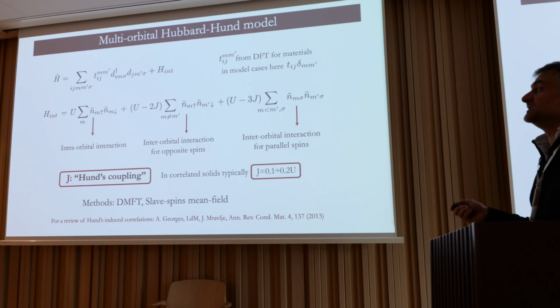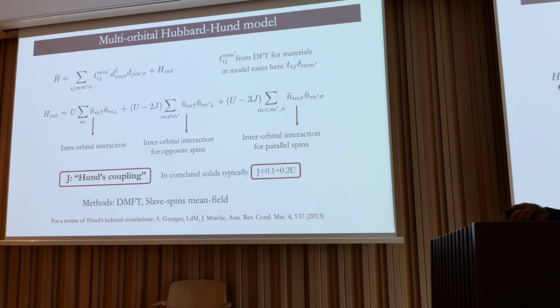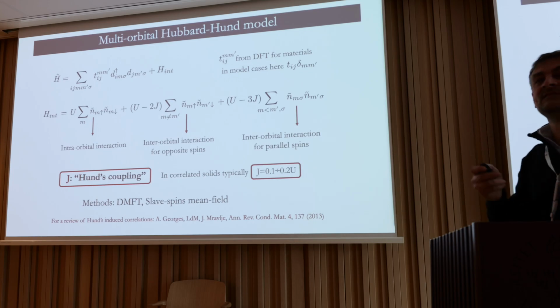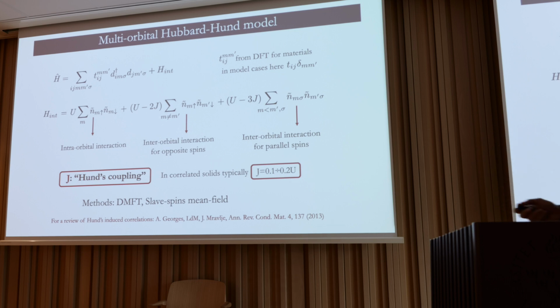This is the simplest form that does the trick. Of course, the interaction also has off-diagonal terms, but we neglect them here. They're only quantitatively important a little bit, but qualitatively all I'm saying can be done with this kind of interaction, where you have repulsion of the electrons in the same orbital, parameterized by U, and then a reduced repulsion when the electrons are on the same or on different orbitals on the same site, and even more reduced if they're aligned their spins by being in different orbitals.